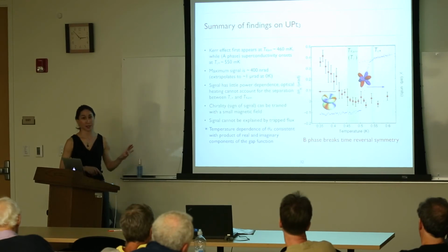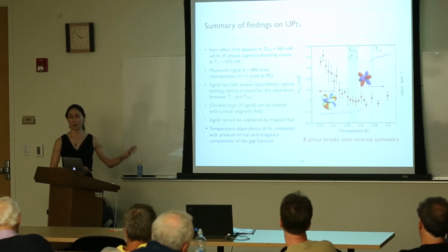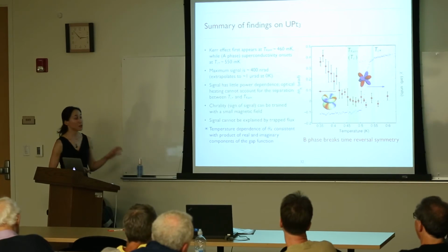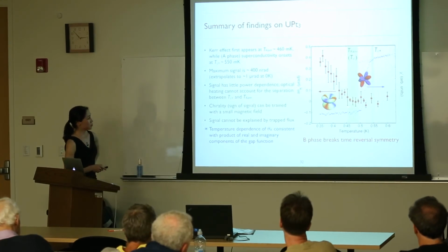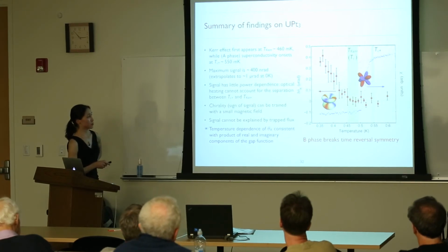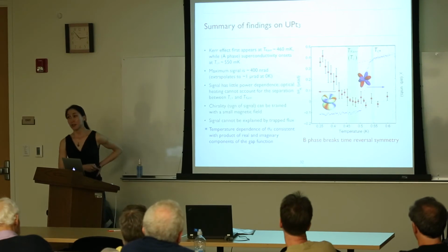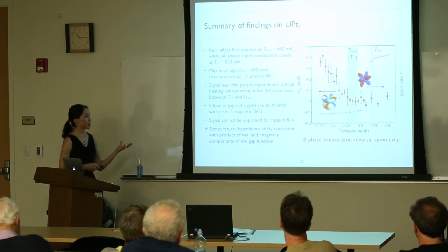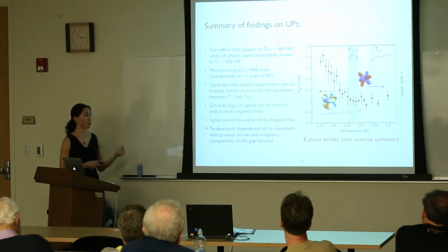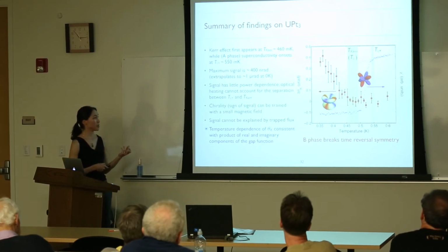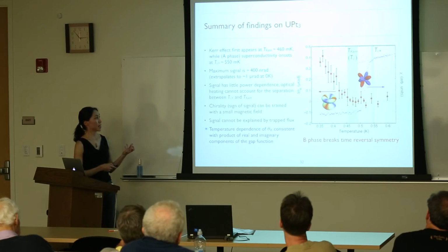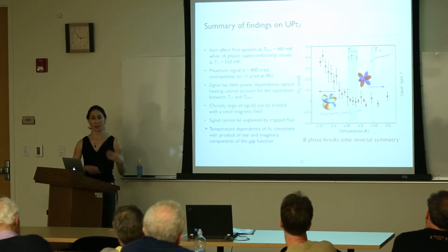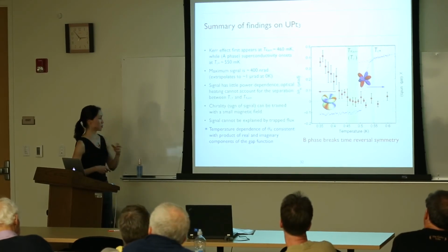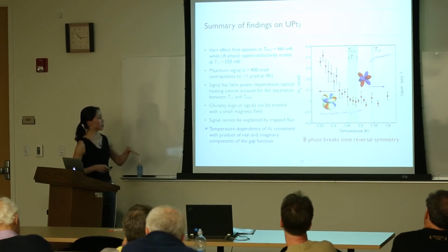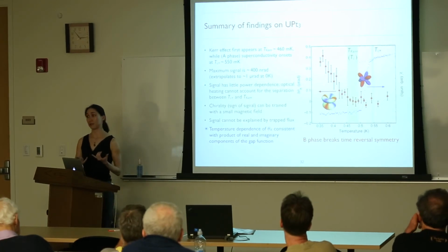There is a second part of this that I didn't want to get into because I was afraid I wouldn't have time. But I thought I should at least mention that you can look at the temperature dependence of this kind of signal. It's a little hard to do great fits because the error bars are so large. But there are people who have thought about how you actually get a Kerr effect and what the temperature dependence of such an effect should be. At the very least, what we have so far is consistent with the picture that's come out of a couple of groups wherein the Kerr angle goes as the product of the real and imaginary components of the gap function.